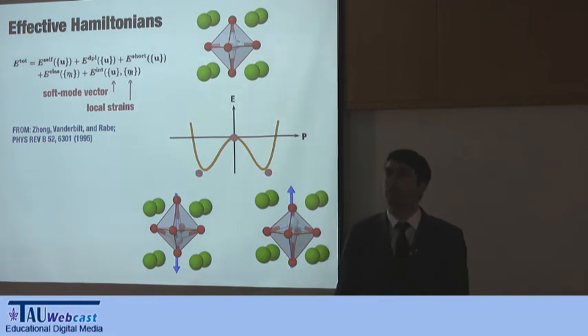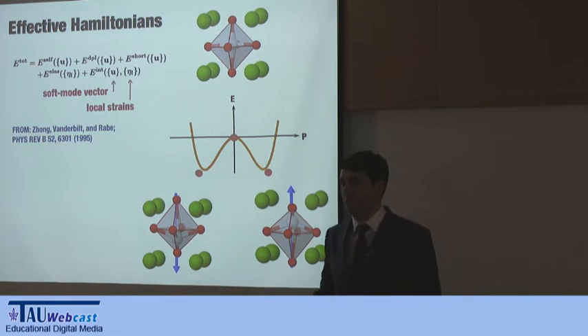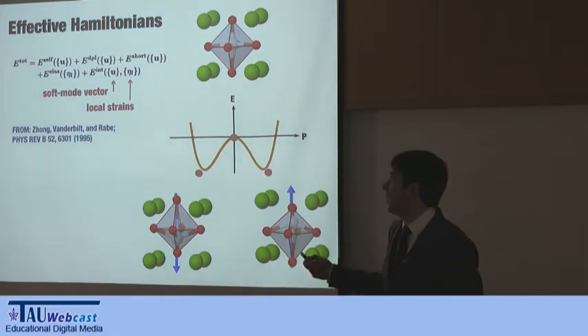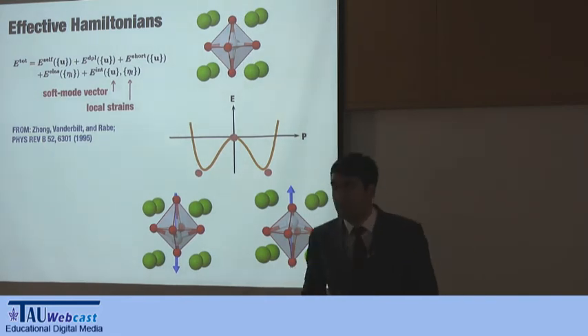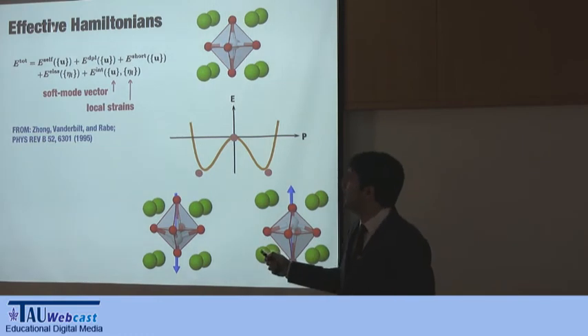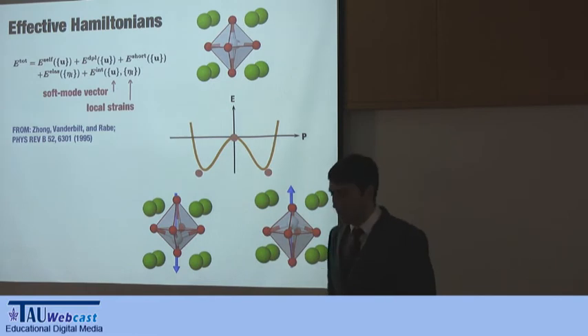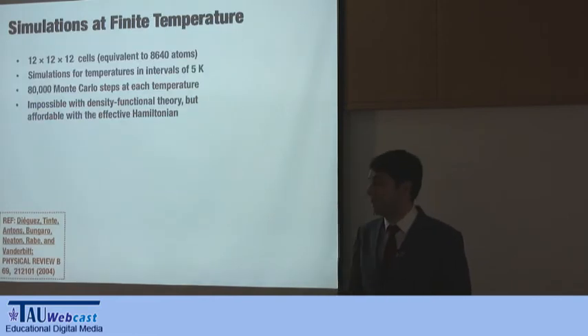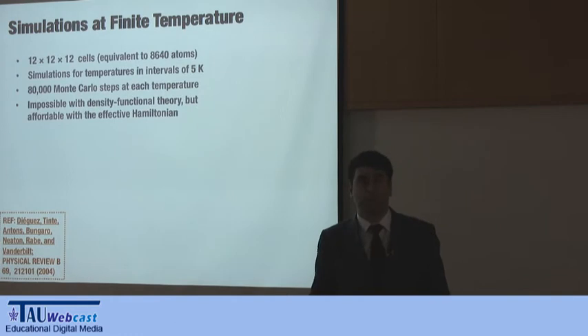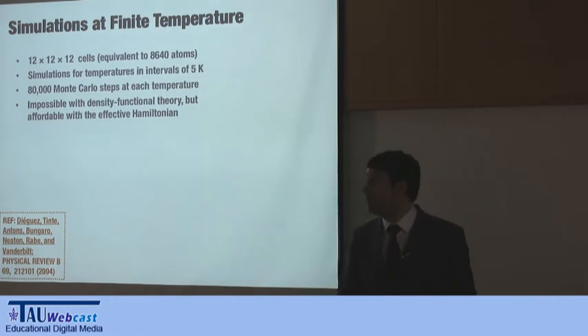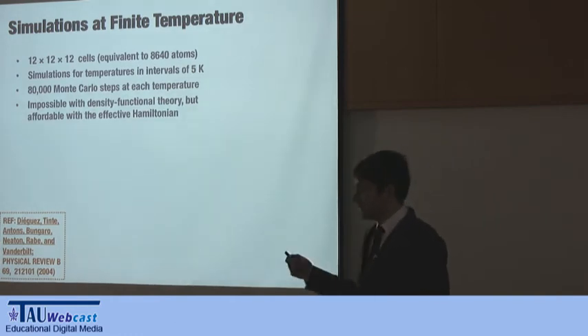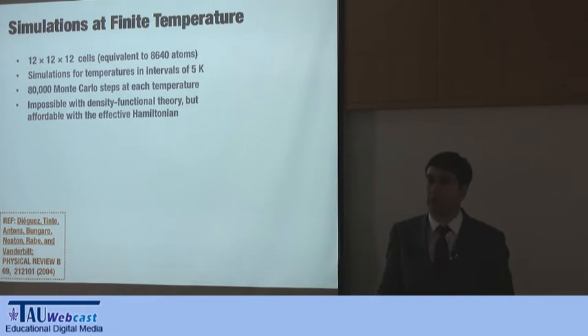So instead of using groups of 5 atoms with their electrons and everything, you just use a component in that displacement. So for every cell, you allow it to move a little bit. Then you build your energy, in a sensible way, to take into account these main variables. And with this, you can evaluate the energy many times in a cheap way. So you do this, in this case, with a so-called Monte Carlo method.